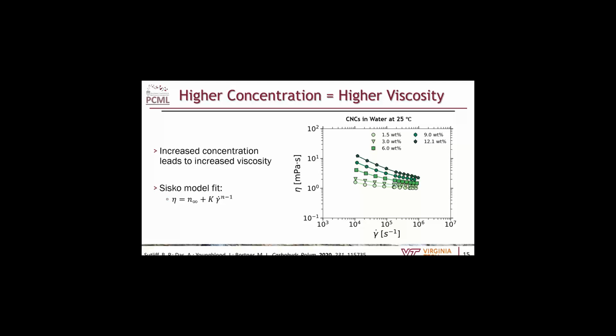If you notice above about 10 to the 5th reciprocal seconds, you'll see a decrease in the slope, sort of a plateauing effect. Especially the 1.5 weight percent, which is the most similar to our water, it's starting to plateau at about the viscosity of water, which is 1 millipascal second. So what we believe is at a certain point, the viscosity of the water dominates all of our other interactions because you can no longer shear thin.